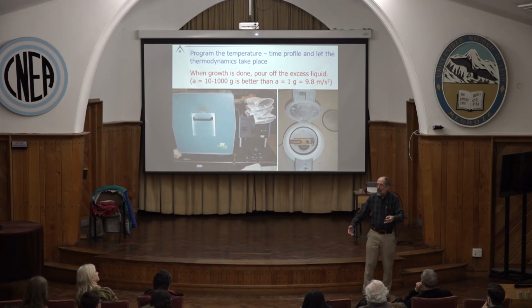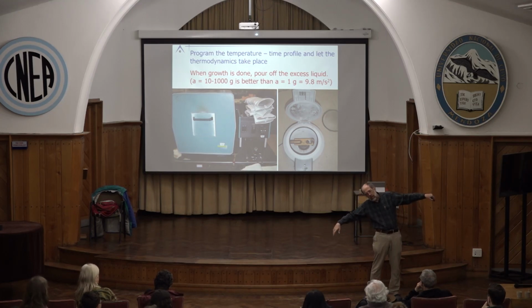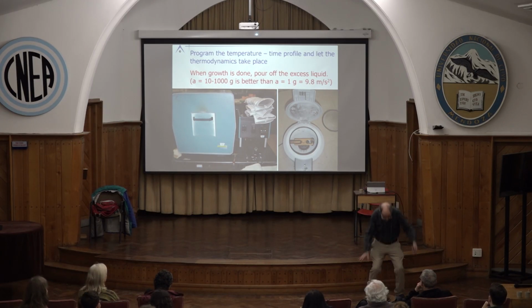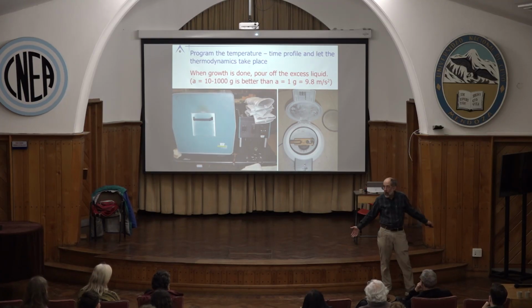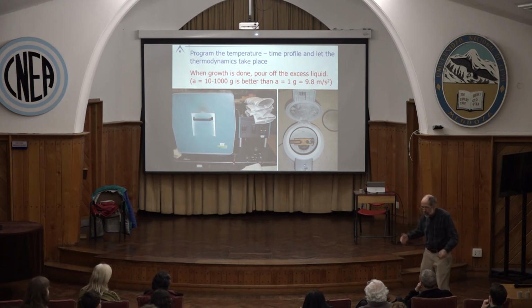Now, if you step out of the shower and there's no towel, you can just go, am I dry yet? It takes a while. Or, even without a towel, you can just do something like this, and you can get a lot of the water off. Water is not that viscous. Liquid antimony is rather viscous, so the way to really do this is to take your ampule, invert it into this, you got that little cushion, and use the centrifuge, and get somewhere between 10 and 1,000 G to just squirt all that antimony to the other side.